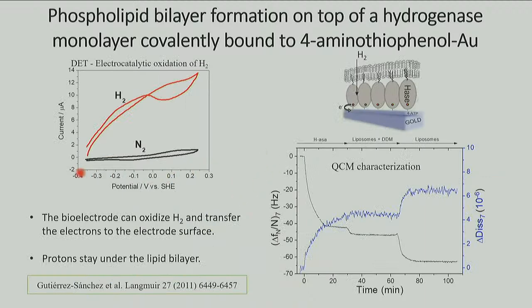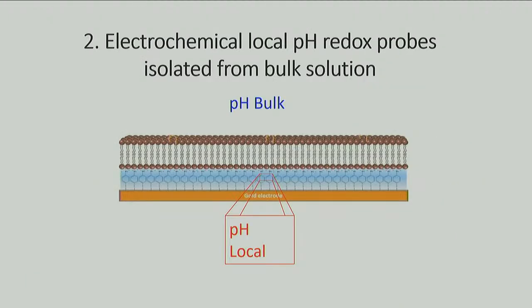This is the electrochemical response. When we give hydrogen to the system, we pump hydrogen inside, we can see the oxidation of hydrogen. But if we put nitrogen, there is no electrochemical response because the enzyme is not oxidizing the hydrogen and giving us current. We also wanted to see if we need a proton gradient, so we need a way to look.